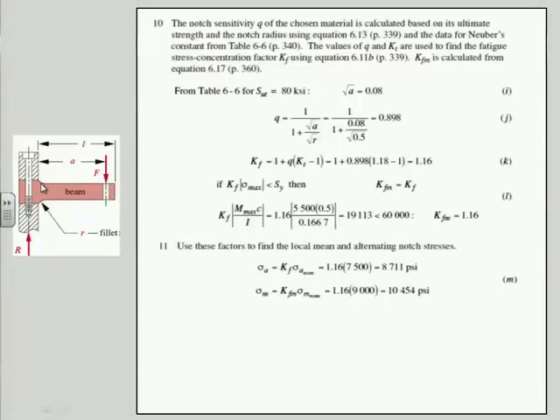Now, don't get the idea that these are fictitious increases in stress. There really is higher stress in the notch. And if you did a finite element analysis of that part under that loading, it would tell you there's more stress in the notch. It's really there, and we're just making an estimate of that. These factors came up long before finite element was thought of. Finite element's been around about 40 years, if that, maybe 30.